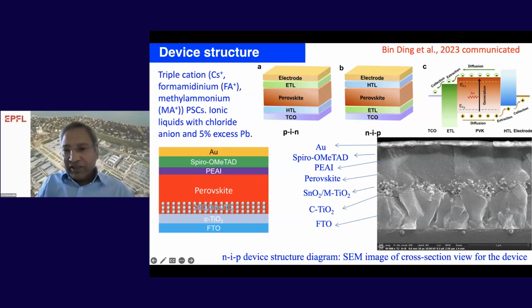Now if you have this ETL layer, the absorber layer and the hole transporting material, when you shine the light, the perovskite gets excited. The positive charges are in the valence band and the electrons are in the conduction band. The conduction band is well aligned with the electron transport layer, so electrons are injected into the ETL layer, and the positive charges are extracted into the hole transporting material.